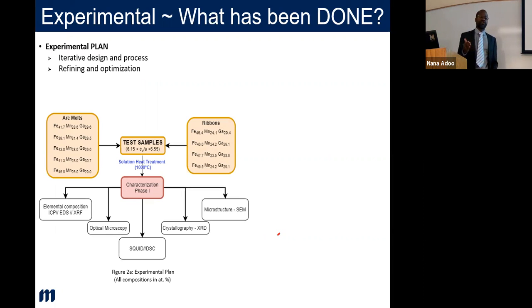looking all through the literature of the materials which seem to transform by the data they produced, got all of them, and then started getting the hysteresis from all of them, calculating the hysteresis. I came up with this iterative process by sampling them within these 10 sample bandwidths, going through a solution heat treatment, and then using characterization techniques for my analysis, either through EDS, XRF, and then ICP, from which I will use the XRD to confirm a lot of the phases that I'm looking at.